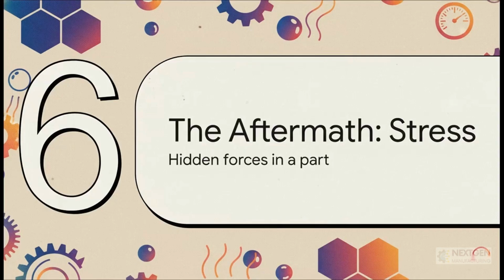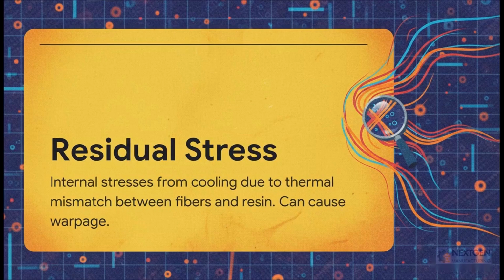You've won the war on voids. You pull a beautiful, visually perfect part out of the autoclave. The fight's over, right? Not quite. There's one last, hidden challenge still waiting for you. As that part cools down from a blistering 350 degrees, a brand new conflict kicks off: residual stress. You see, the resin wants to shrink a lot as it cools, but the carbon fibers inside it, they barely shrink at all. This creates a microscopic tug-of-war throughout the entire part, locking in stress that can cause it to warp or even develop tiny microcracks down the line.